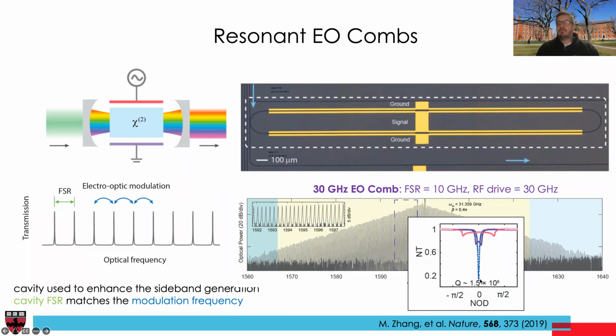So in blue, I'm showing you the transmission spectrum of the resonator with RF off. This is the typical resonance dip that you see. One of the resonances, there are many of these resonances, I'm only showing one. The typical resonance dip that corresponds to a ring resonator. In this case, we carefully designed the coupling between the ring and a waveguide, so the ring is so-called critically coupled. So basically, transmission is 0 on resonance and 1 off resonance. And in order to do that, you match the losses of the ring resonator to the coupling loss.